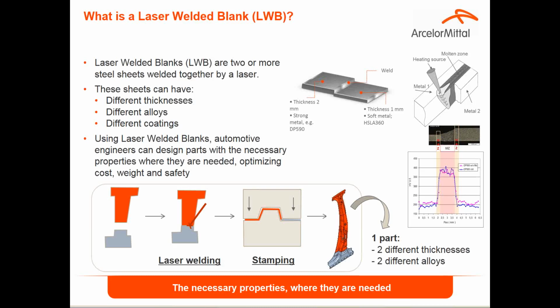Hello everybody, Luciano Marinoni speaking. I'm going to show you what a laser welded blank is. It's in fact a part made by 2 or more steel sheets welded together by laser, in which we can combine different thicknesses, different alloys, grades, and different coatings. One important fact to highlight is that the weld seam has a very narrow heat-affected zone. And then the transition between one grade or one thickness to the other is really narrow.